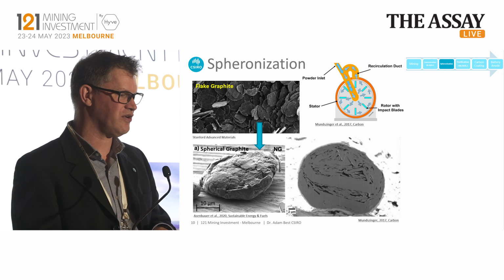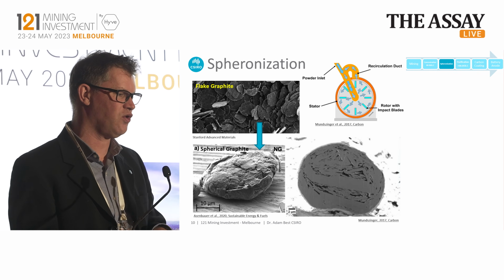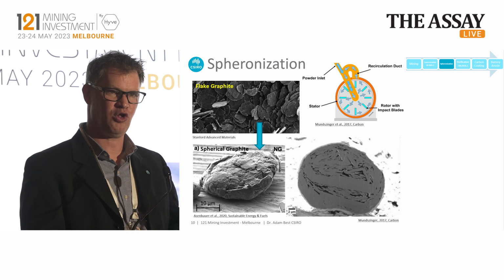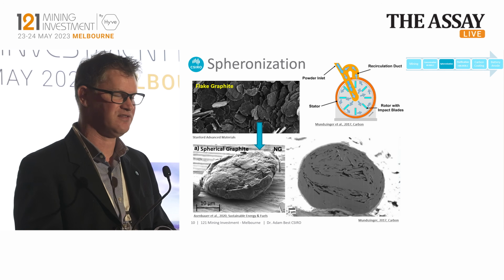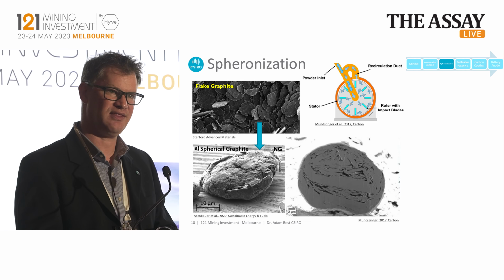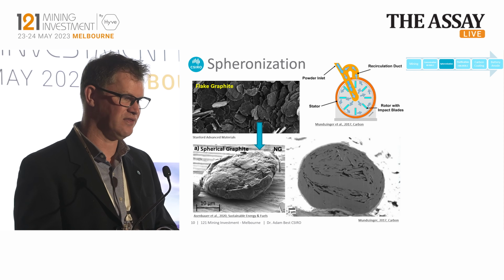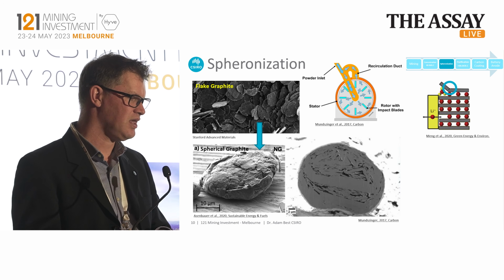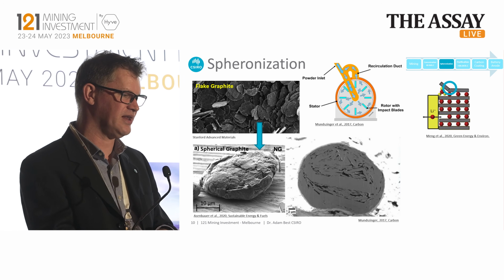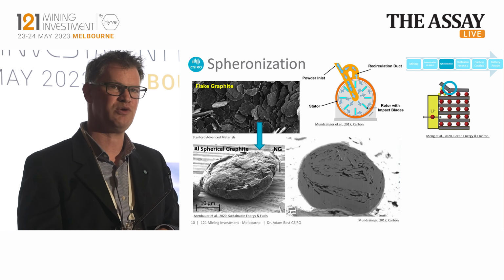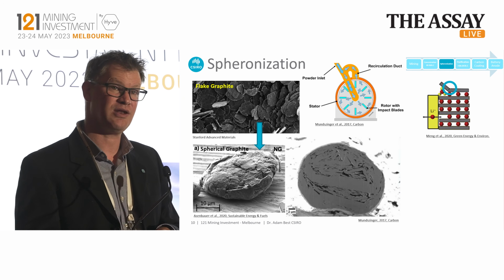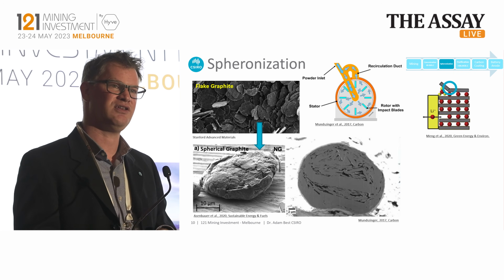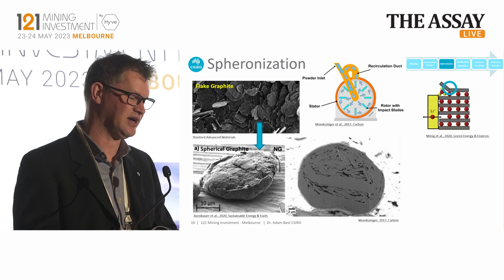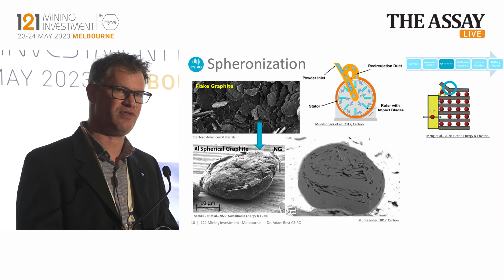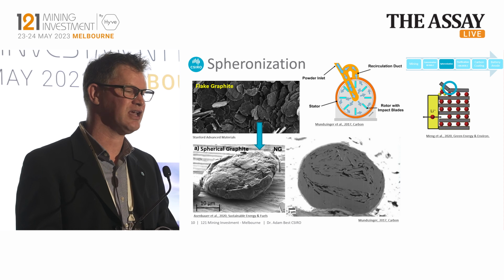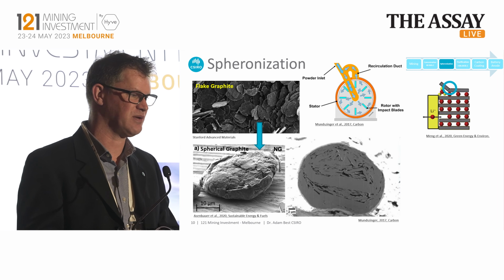And so what you end up with, if we cross-section it, is this. You can see here all the flake particles are all being rolled in till you get this round ball. So that's just a whole bunch of graphite flakes packed in together, and that's where all the lithium is stored inside the cell. And so one of the things that we're trying to avoid here is also damaging the flake. So the more you process this material, sometimes the more you can make it amorphous. And when it becomes amorphous, then you don't have storage capacity, but it will be electrically conductive. So being able to balance the amount of processing that you do is really critical in order to maximize the storage capacity of graphite.